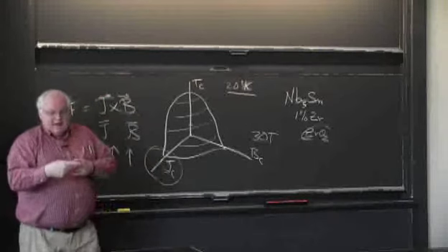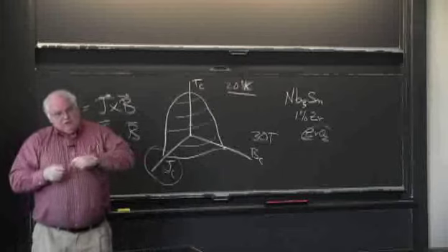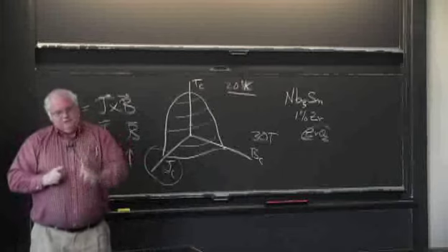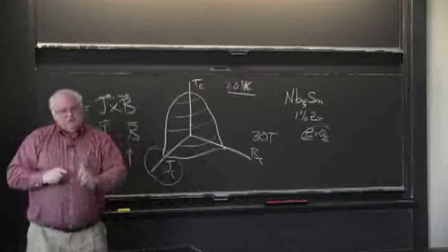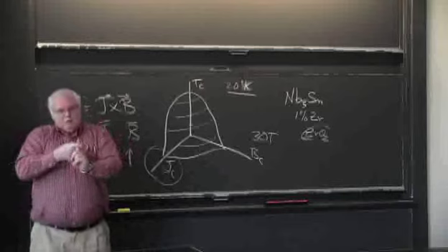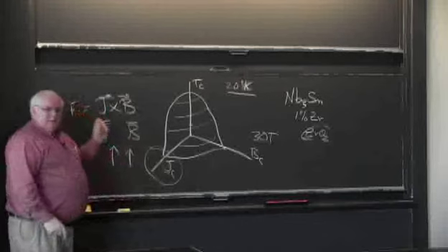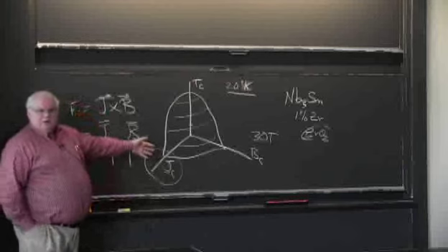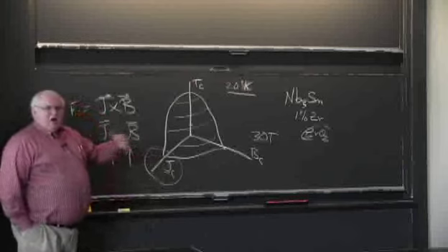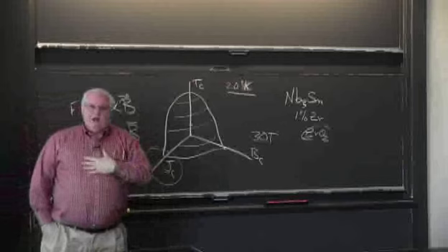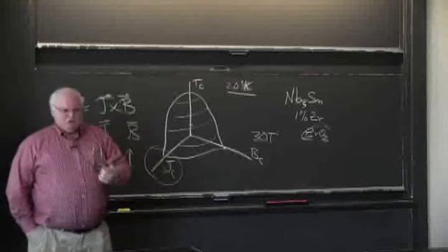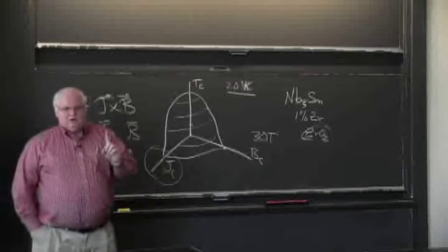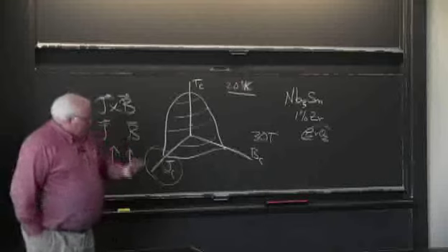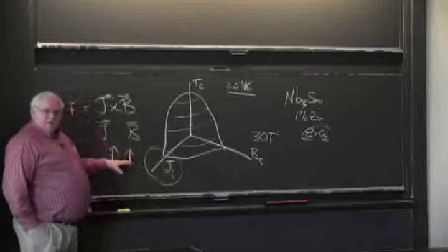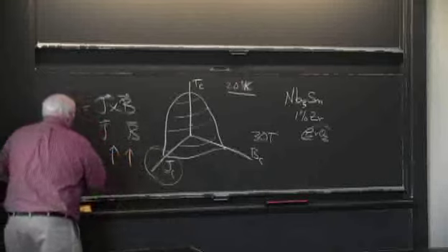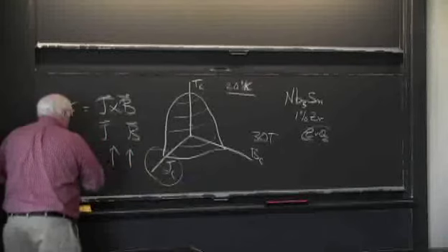But if you ever build a magnet, it's going to be wound, and the current's going to be going in the circumference, and the field is going to be going axially. They're perpendicular, which is the maximum force to destroy the critical current. And if I had gone to a superconductivity conference and presented a paper where I measured the critical current when the two were parallel rather than perpendicular, I would have been laughed out of the room.